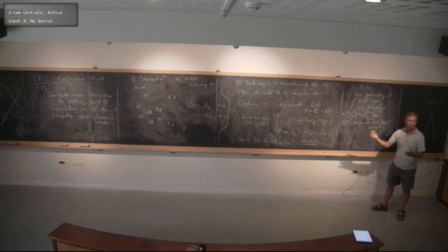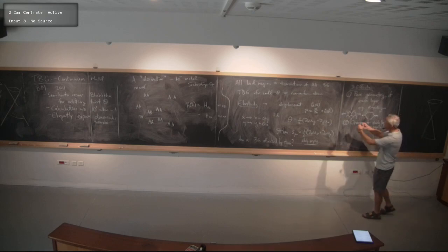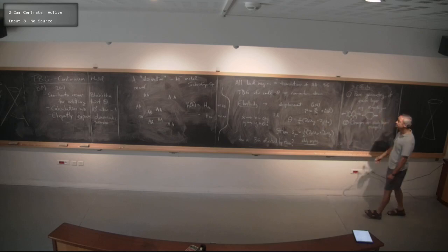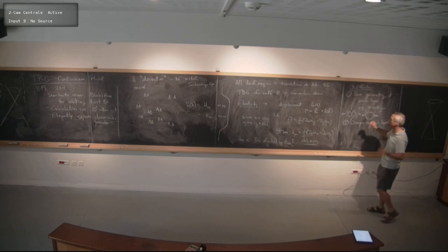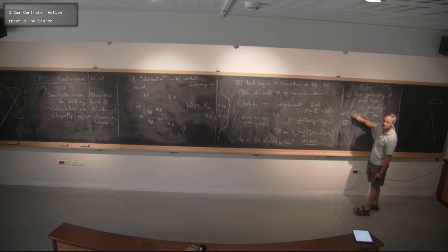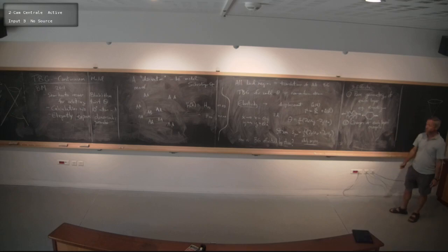So this is the other type of effect I mentioned, that the bond length changes, that changes the hopping. Okay, that's the most important physical effect of straining a layer. For example, if we did this, we wouldn't be stretching these bonds very much, but we'd be stretching these somewhat. So in the simplest tight binding model, you would say, well, now this hopping is different from this hopping. We'd have a T here and a T tilde here. And they differ by an amount proportional to the strain, generally.